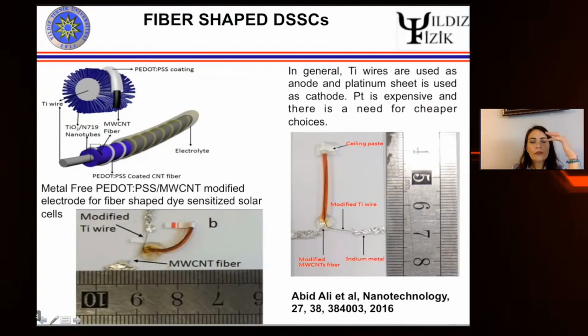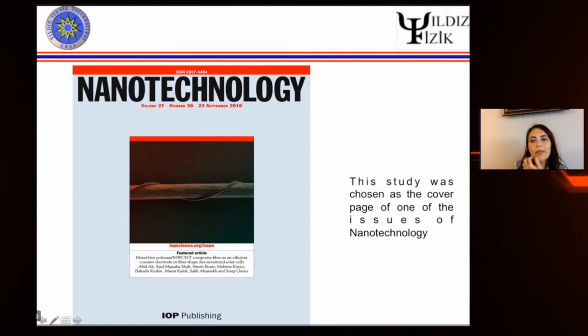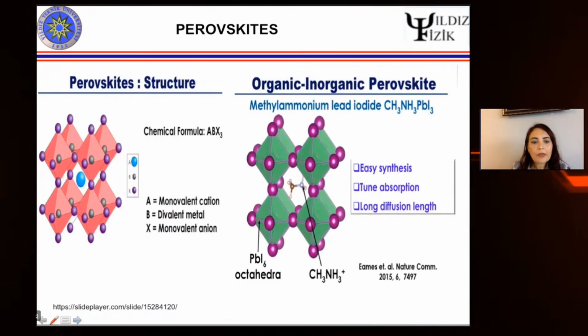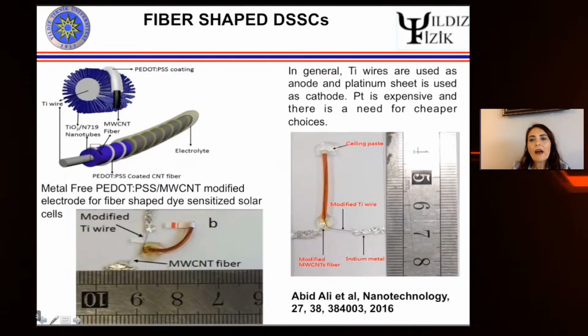To add to this dye-sensitized solar cell, Abid Ali, this is also a work from our group. Again, he was dealing with these cost issues. He was using platinum electrode to fabricate the dye-sensitized solar cells. When he joined my group, we were using a lot of PEDOT:PSS, and he modified his multi-wall carbon nanotubes together with PEDOT:PSS for this dye-sensitized solar cell. This has been the cover page of Nanotechnology. And we really achieved high efficiencies. It was almost 4%, comparable to the ones where we used platinum as electrodes.